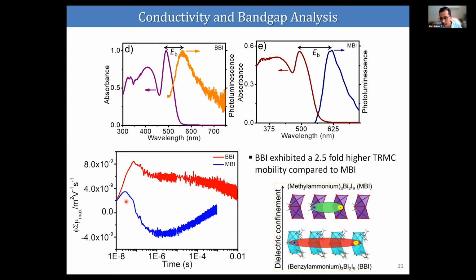And so we can say that the exciton separation efficiency is very low in the standard material, but it is relatively higher in our material because of the polarizability of the organic cation. So that can assist the exciton separation in our material. So that is our finding. And the next thing, we try to understand the electronic band structures.